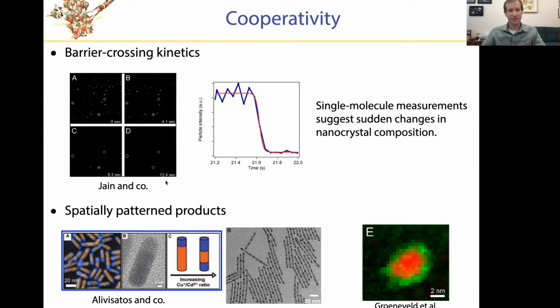Furthermore, the products of this are not always as simple as a front that's simply progressing into the interior of the nanocrystal. Sometimes that's the case. This is an image showing a core shell structure that has resulted from partial cation exchange. But partial cation exchange can also give much more exotic structures. In the case of these nanorods here, replacing cadmium by copper gives rise to these amazing structures where domains of the new material are now spaced relatively evenly along these nanorods.